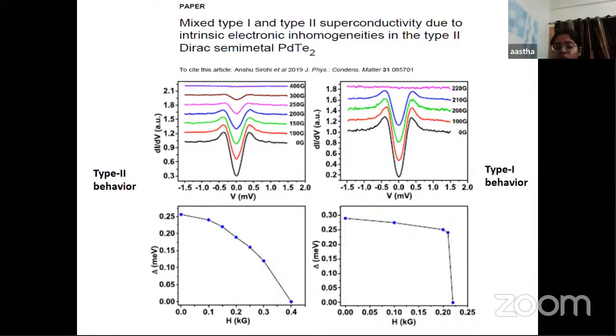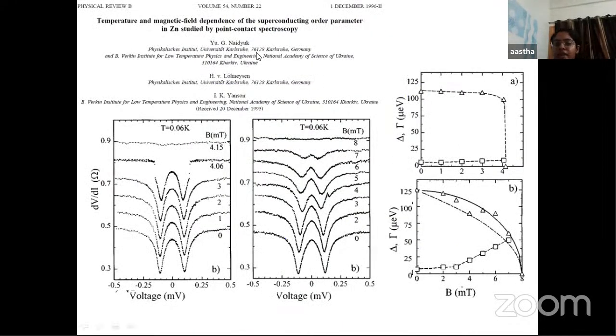The distinction of type 1 and type 2 superconducting behavior by these spectroscopic measurements was already reported in the past by Naidyuk et al. in 1996, where they probed two different regions in the presence of a magnetic field. What they observed is that in one region, this double minima structure abruptly decreased with magnetic field, and the variation of the superconducting energy gap with magnetic field was seen to be like this, while in certain other regions the point contact spectra evolved smoothly towards the normal state with increase in magnetic field, and in such a case the superconducting energy gap varies smoothly with the magnetic field.